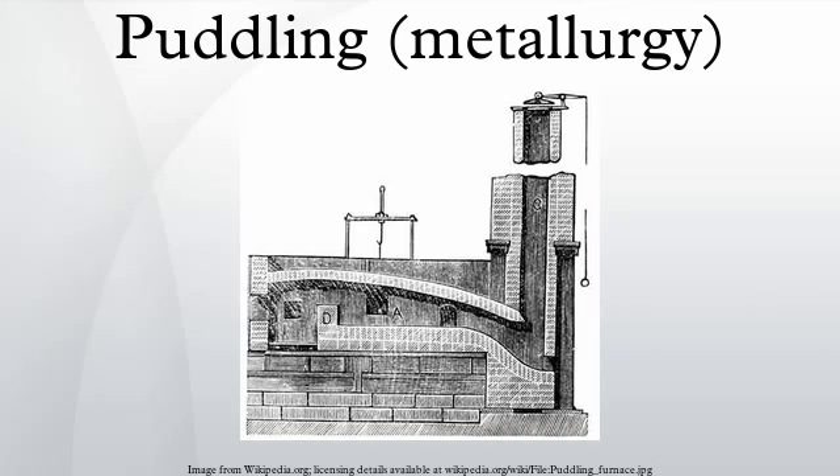Due to the great heat required to melt the charge, the grate had to be cooled — either by running a constant flow of cool air on it or by throwing water on the bottom of the grate. The fireplace used a cast iron grate which varied in size depending on the fuel. If bituminous coal is used, the average grate size is 60 cm by 90 cm loaded with 25–30 cm of coal. If anthracite coal is used, the grate is 1.5 m by 1.2 m, loaded with 50–75 cm of coal. A double puddling furnace differs mainly in having two work doors, allowing two puddlers to work simultaneously, producing twice as much wrought iron while being more economical and fuel efficient.